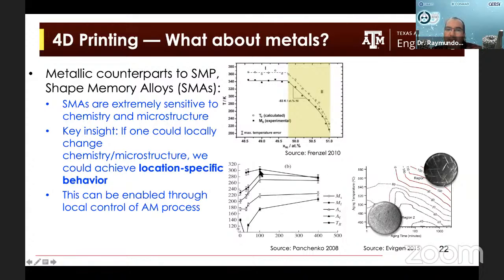Here on the right side, I have a contour plot of transformation temperatures as a function of aging temperature and aging time. So this particular alloy undergoes a precipitation reaction. So you have precipitates that come out of solution, and depending on the amount of precipitates and their shape, you can actually change the transformation temperature dramatically by just controlling the heat treatment, right? So clearly, these alloys are very dependent on composition and microstructure.